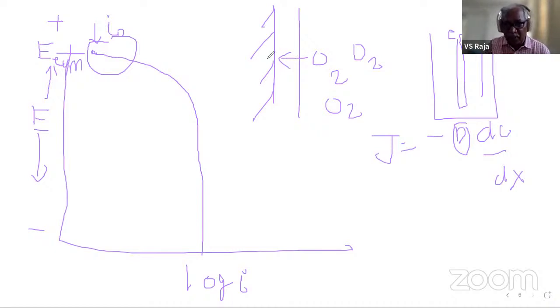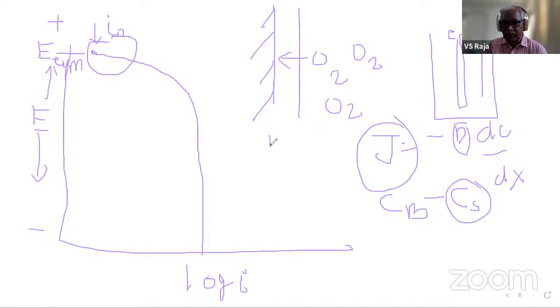Now, when the concentration is zero, what is dC? Concentration of oxygen in the bulk minus concentration of oxygen at the surface, right? Now look at this value. This value, C bulk minus C surface, becomes the maximum when the surface concentration becomes zero. When the surface concentration becomes zero, the dC becomes the highest. The flux becomes the highest. What is flux? Flux is nothing but moles per area and per time, isn't it? And moles is related to current, right? So when the surface concentration becomes zero, maximum flux can occur. Beyond that, you can't do anything.